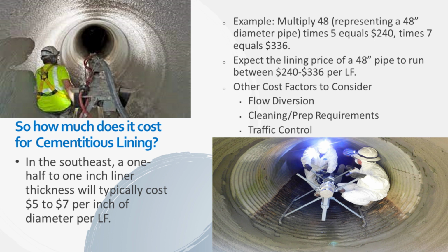And just to simplify that a little bit, basically you take the diameter, this is a 48-inch diameter pipe, you multiply that 48 times 5, which would equal $240, and then 7 times 48 would equal $336. So that would give you a linear foot range of what cementitious lining would cost, and this would include modest flow diversion, modest cleaning and prep type requirements, and modest traffic control.